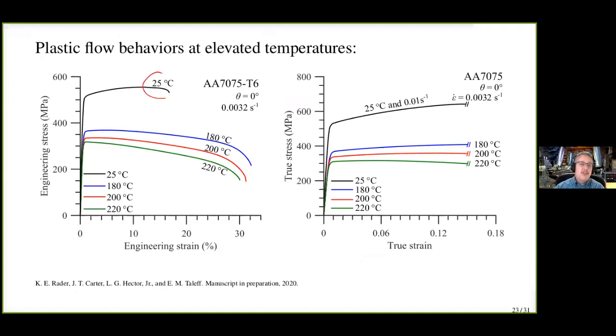Okay, what happens at high temperatures? Here's our room temperature T6 just for reference. Here are the behaviors at 180, 200, 220 degrees Celsius. So what you see is you get that significant drop in strength, but you also get an increased elongation. This is the ductility we're trying to use, and this target temperature looks pretty good. Now, how do we predict the flow behaviors? Well, plastic flow modeling is complicated. Nobody does a very good job of plastic flow modeling at warm temperatures, partly because we don't understand the physical mechanisms by which plastic flow occurs at room temperature very well. So in this case, Mother Nature is actually pretty kind to us.